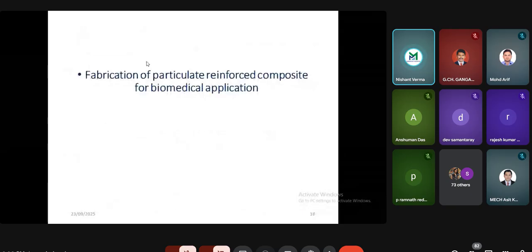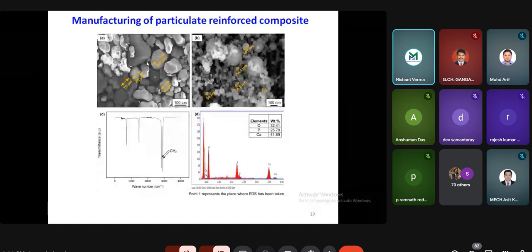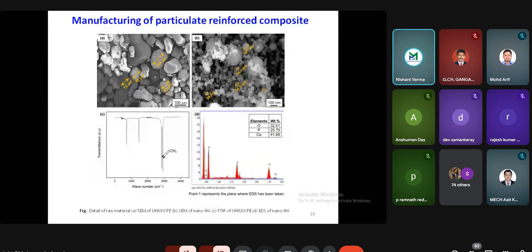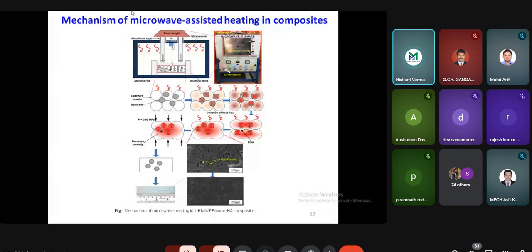So basically, now I would say how we have manufactured the particulate reinforced composite by microwave energy. As in the slide you can see that there are particles of matrix as well as the reinforcement. The reinforcement is hydroxyapatite, because we have used hydroxyapatite for biomedical applications. Here we see the scanning electron microscopy of ultra high molecular weight polyethylene. It is in powder form, and the nanohydroxyapatite is also in powder form. So how have we made use of microwave transparent material to heat with the microwave and to maximize the consumption of microwave for the heating?